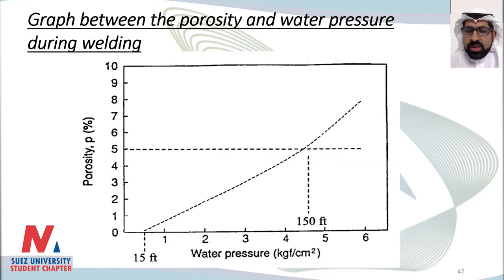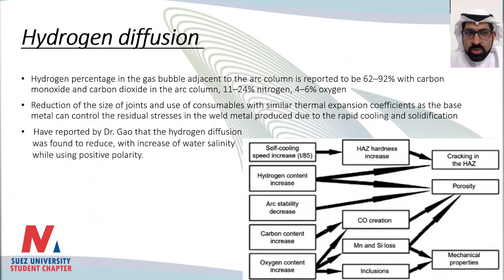Next. This is a graph showing that the deeper you go, so the more water pressure you have, the more porosity you're going to have. We just explained that in the previous slide. Next. So the hydrogen diffusion figure summarizes everything. If you have fast cooling or quenching, then we're going to have a very hard heat affected zone, and that very hard heat affected zone would result in cracking, hydrogen cracking, hot cracking or even cold cracking. If we have more hydrogen content, then again we are going to have cracking in the heat affected zone, or this hydrogen will result in gas pockets or porosity.